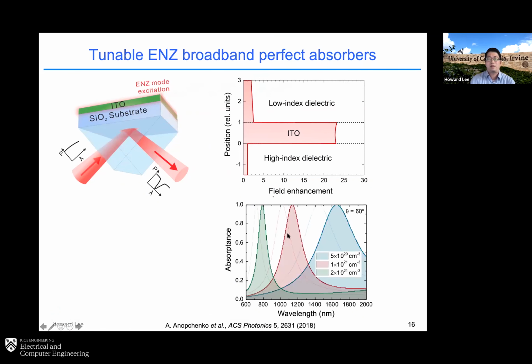What that means is that you can also use it as a strong absorber. If you look at the absorption, you can have a perfect absorption band, and depending on the carrier concentration, you can tune this perfect absorption band to different wavelengths you want as well.